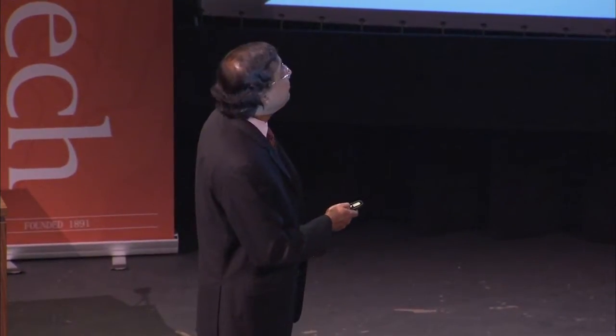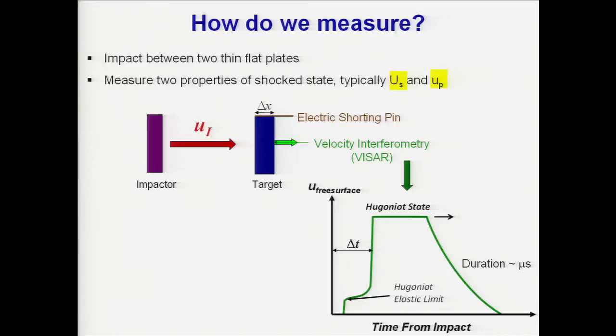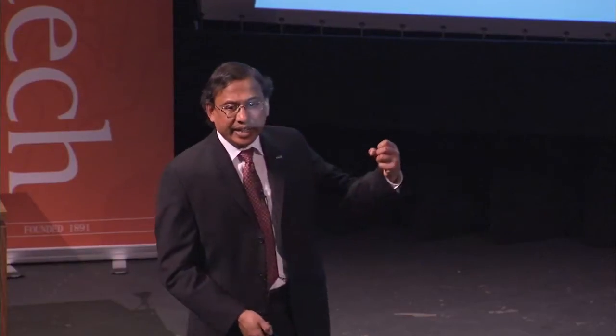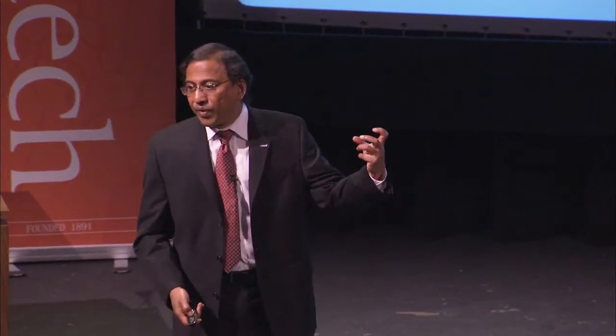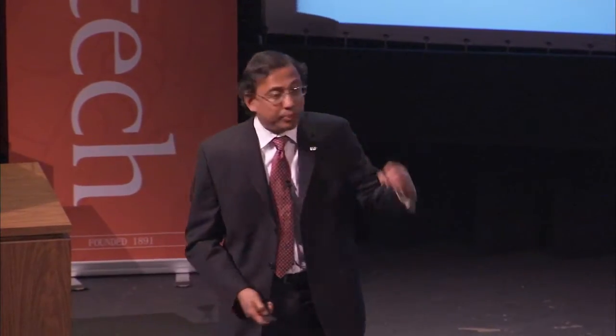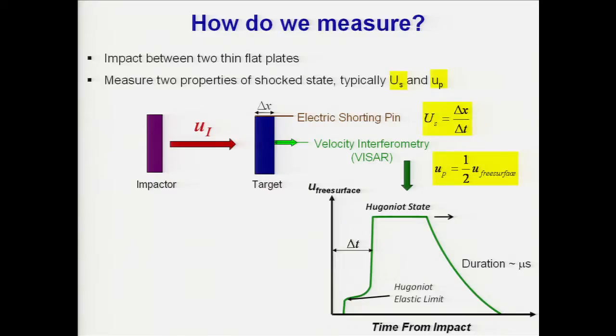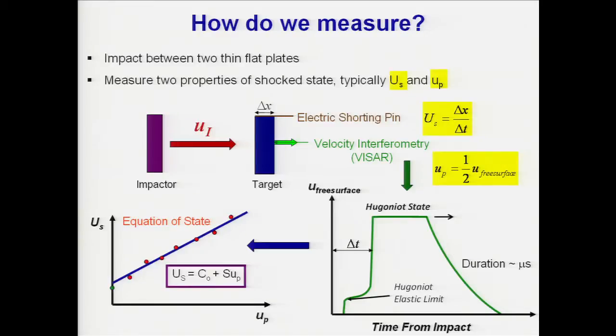So when we know this, the signal looks like this. There is the wave which arrives, so we know the wave arrival time, and the material shocks up and reaches the so-called Hugoniot state, which is the pressure we are interested in. But we are also interested in the structure of the shock wave, and the typical duration which we generate is a microsecond. So we are creating this million atmospheric pressure for a microsecond, a very, very short time, and we try to probe the material properties at this small scale. We can measure the shockwave speed by dividing the distance by the time of arrival. That's the shockwave speed. And we measure the particle velocity using the velocity interferometer, which is a wide-angle Michelson interferometer, which we use for measuring during the short times. And what do we get?